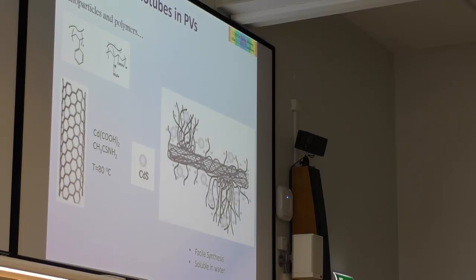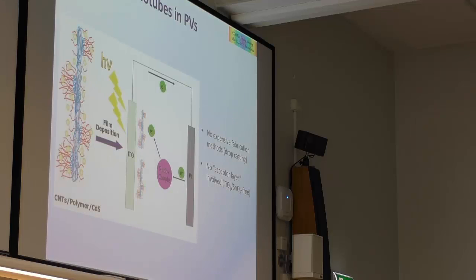So you have a water-soluble nanotube wrapped around with polymer and cadmium sulfide nanoparticles along the sides of the nanotube. So this synthesis is very easy. You have materials that are soluble in environmentally friendly solvents, and this can be used directly onto an ITO, so you don't need any expensive fabrication method, just drop cast these nanotubes onto an ITO, onto a transparent conductive electrode.